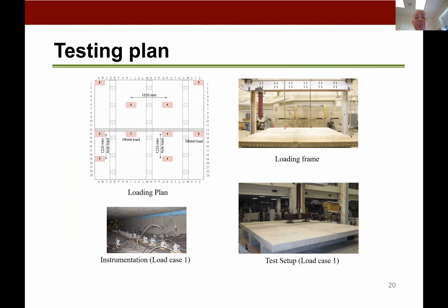So that led to our testing plan. We had essentially 7 load cases for which we followed the AASHTO wheel load, where we looked at the trailing wheel loads for the interior span for load case 1. Load case 2 looked at the wheel load pad sitting right on the seam on the edge, right on the overhang with just a single point load, to look at what an equivalent moment could look like if you were to have some type of impact on the barrier, and then converting that into an equivalent moment and a force of what could be felt there.